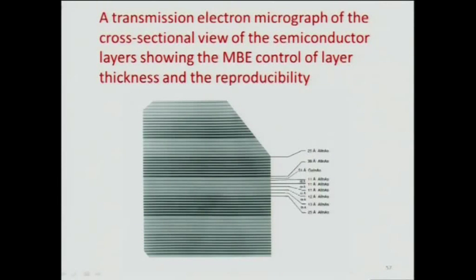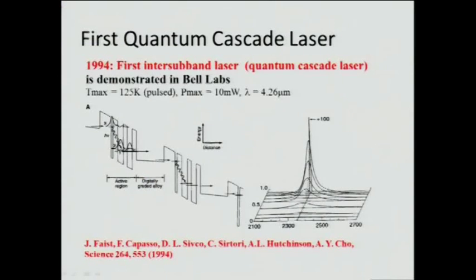And of course, the structure, you can see the demonstrating on MBE growth of these structures, and the reproducibility, control of layer thickness. Some of these layers are only a few atomic layers thick, that we were able to fulfill what Jerome was asking for. Now, of course, the first announcement of that structure, you can see that Jerome published here, that what he did is he added to the regular superlattice structures an adjacent 28 angstrom quantum well. As we know, he tried to make it population inversion.